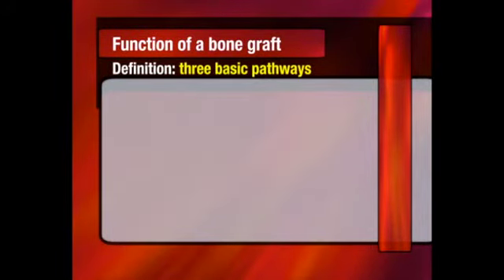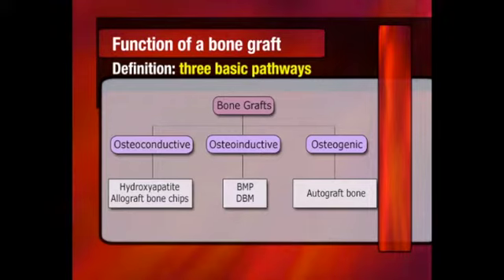The function of a bone graft may be defined through three basic pathways. 1. By adding a competent osteoconductive surface for migration and attachment of pluripotential mesenchymal stem cells. 2. By implanting pluripotential mesenchymal stem cells in the injury site, thus the basis for autogenous bone grafting and autogenous cell concentrating systems. And 3. By osteoinduction, using a variety of proteins that coexist in the autogenous bone graft harvest to provide a stimulatory effect for bone formation.